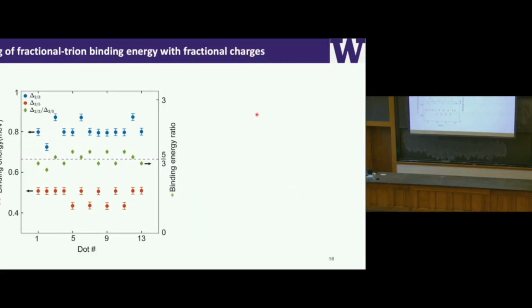So what we did is measure many different traps and compile all this data together. These blue dots represent the binding energy of the fractional trion of the 2/3 state. It's all around 800 microeV. Orange dots represent the binding energy of the 3/5 state, all around 500 microeV. And the green diamond represents the ratio of the binding energy of the 2/3 to 3/5 states. You can see the green diamonds scattered around this dashed line, which is 5/3. That's the ratio of the fractional charge.